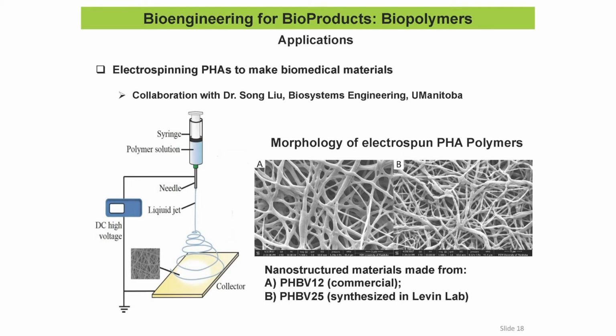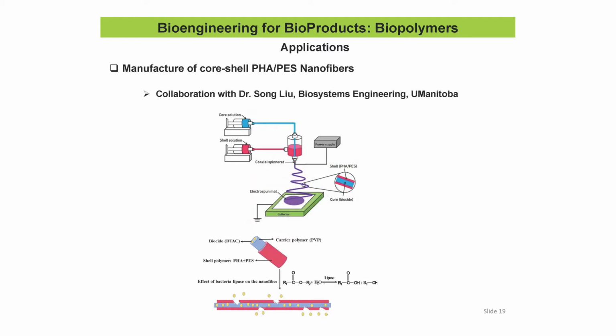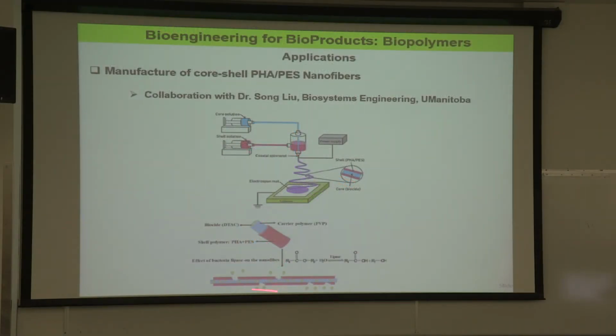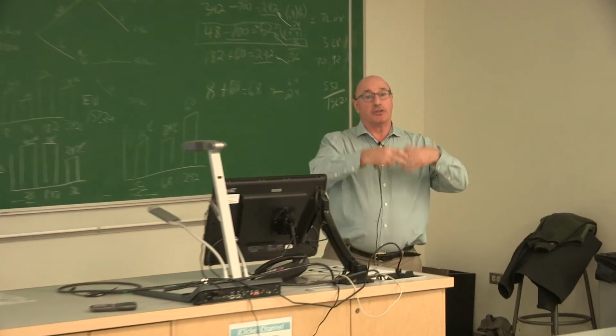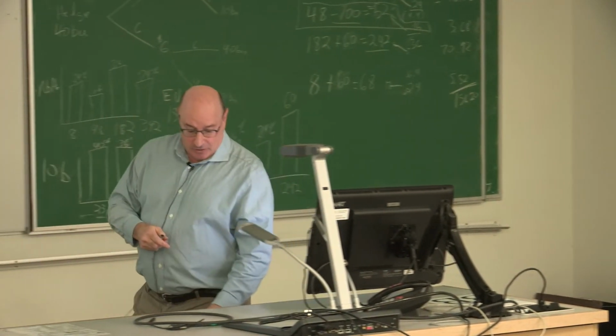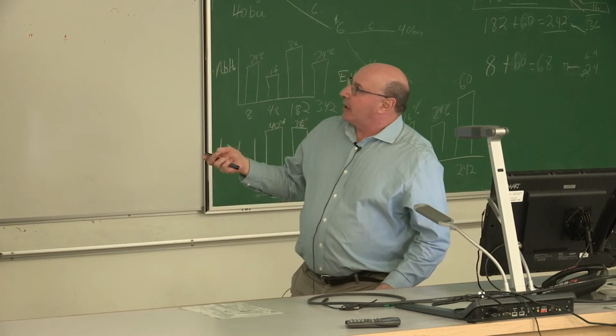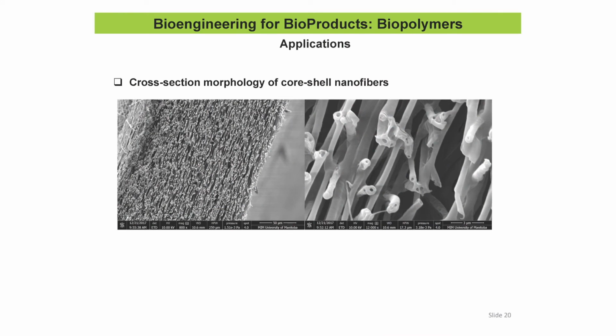And another interesting thing is that he could make these coaxial fibers where you have an outer coating with the PHA and an inner coating with a different polymer that contains a bioactive molecule. And the idea is that you could make these nanostructured materials that contain an antibiotic inside, and if you were using it for wound dressing, for example, if your wound was infected, then the bacteria would secrete an enzyme that breaks down the PHA and creates holes in the shell, releasing the bioactive molecule to limit the growth of the bacteria. Very interesting idea. And this is an electron micrograph of a cross-section of those core shell fibers where you can see the holes with these hollow tubes inside where you would have this bioactive molecule. And that work is still ongoing.